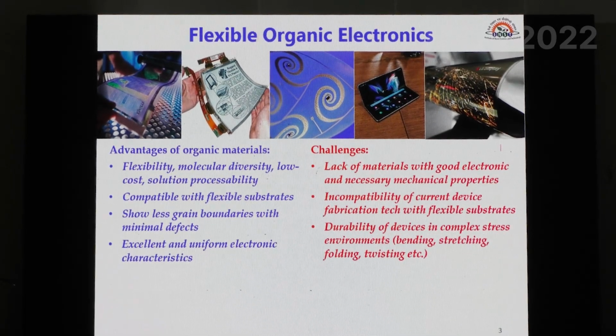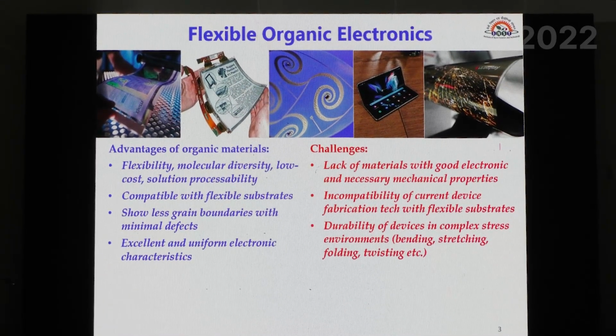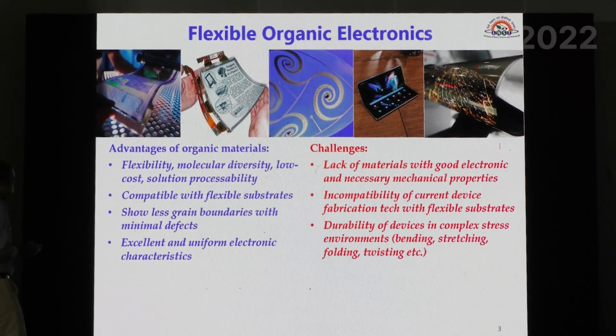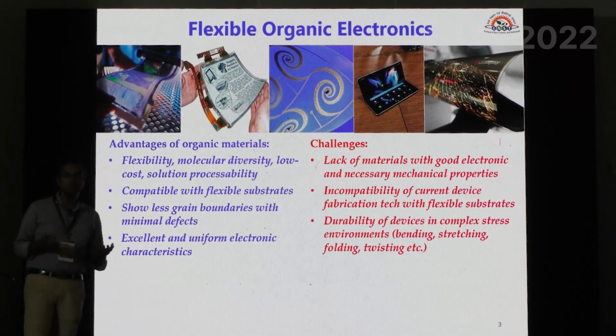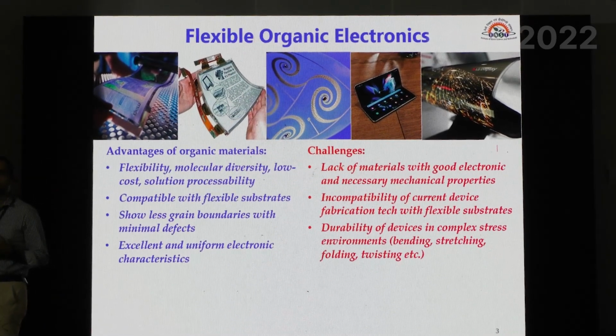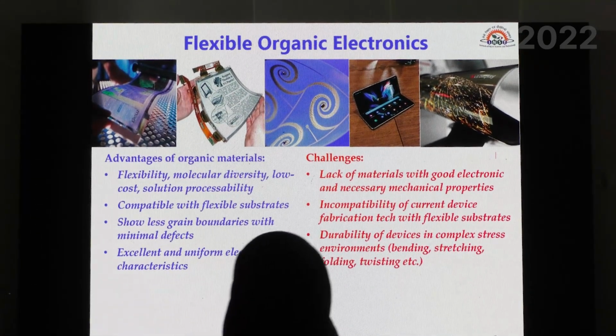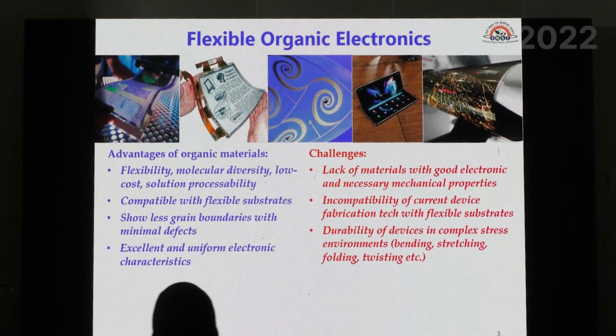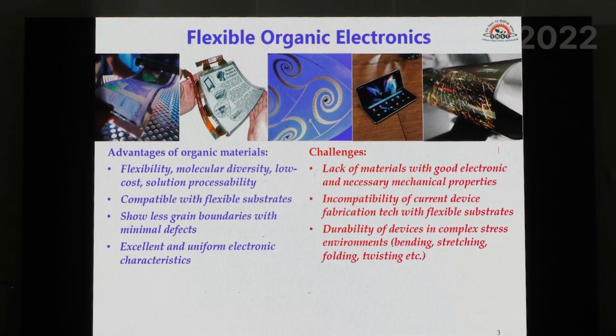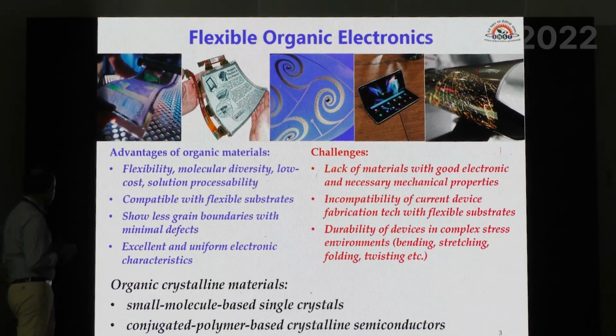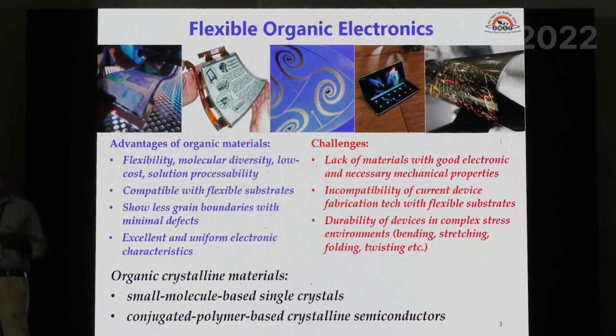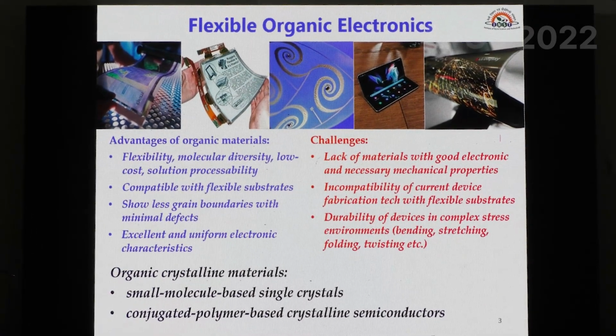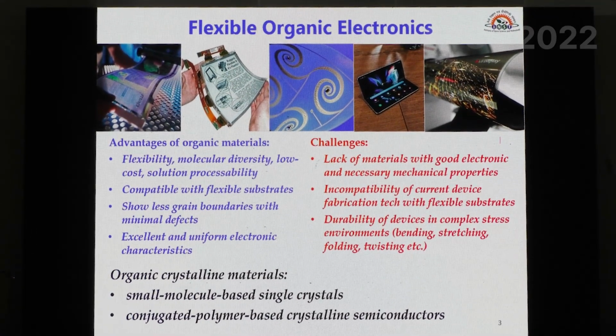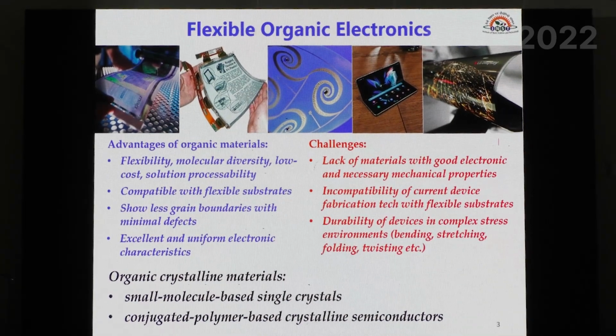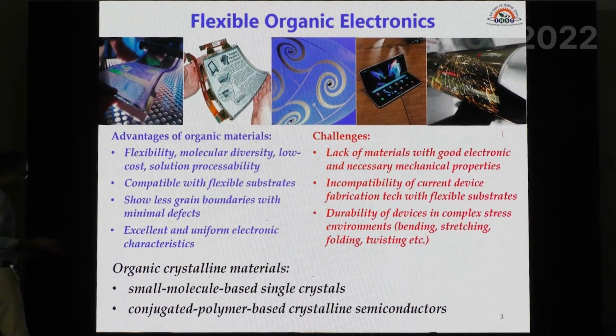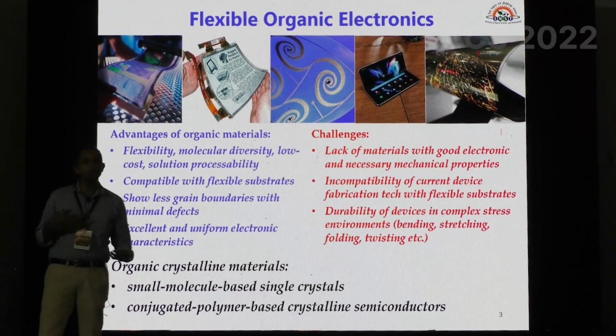And in organic materials, single crystals are much better, because in crystals, you have highly ordered packing, and because of that, the defects are almost absent, and that leads to a lot of good properties like absence of grain boundaries, or better conductivity, or all those optoelectronic properties that are needed for these electronic devices. So that way, small molecule based single crystals are always better, and organic molecules are easy to synthesize, and then functionalization is always easy.